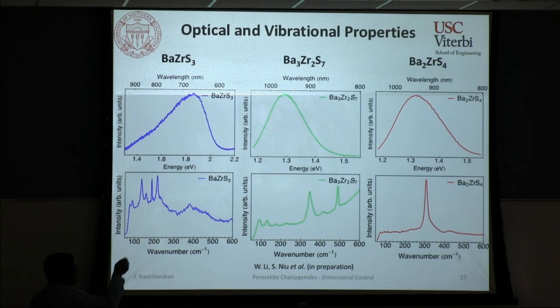The barium zirconium sulfur 3, which you saw in powder form earlier, now shows exactly the same 1.8 eV even in the single crystal form, and the 3-2-7 and 2-1-4, which are the n equals 2 and n equals 1 Ruddlesden-Poppers, show close to 1.3 eV, slightly different in the two cases, but close to 1.3 eV luminescence emission. So that means your band gap is roughly there. It doesn't completely resolve the exact optical gap, but it gives you a ballpark number. Not only that, we are also able to see nice Raman peaks at room temperature for all of these, which tells you that the material actually interacts nicely with light and is of really high quality.